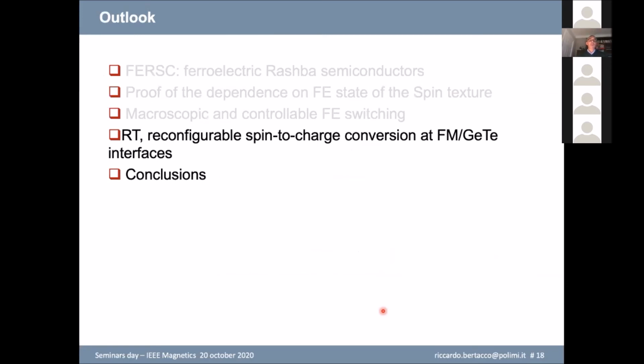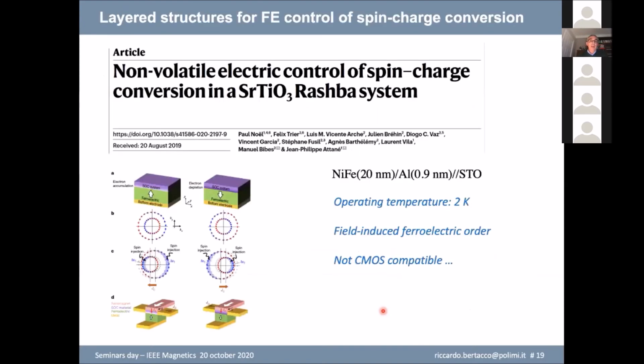So we are ready now for the demonstration of the room temperature reconfigurable spin to charge conversion at the ferromagnet germanium telluride interface. Okay, what does it mean? It means that people would like to achieve a system in which you can play with the spin just by playing with an electric field.